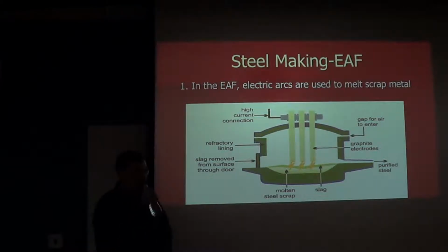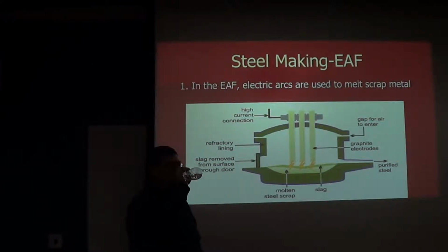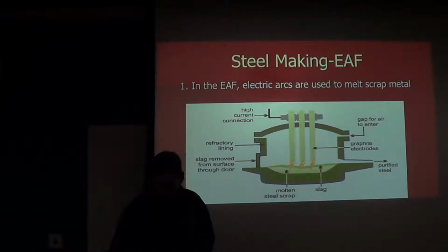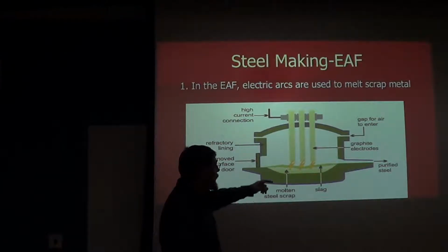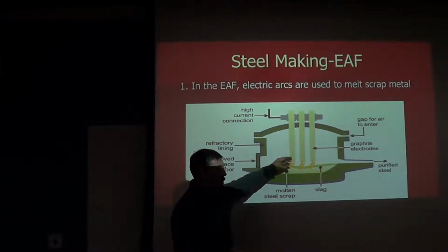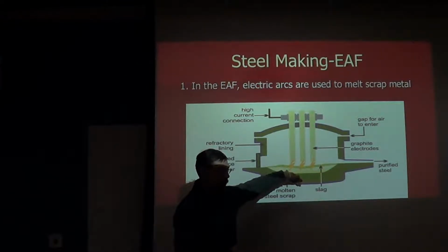How often do the electrodes degrade? I know they're not touching the melt, but can carbon content get added to the steel? Yes, they can. The electrodes are continually eroding. They're graphite, and so they are in fact adding carbon to the liquid bath.